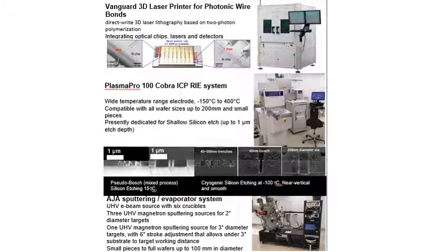The 2 SEM images here are cross sections of etch tests. And you can see on the left side, we are etching trenches as low as 40 to 50 nanometer trench sizes. We are fully clearing them for this 500 nanometer substrate for mid-IR integrated photonics. This next image for this pseudo Bosch is a slot waveguide. So again, it's fully cleared. The side walls are near vertical and a smooth looking profile on both sides, and we still have some resist left.